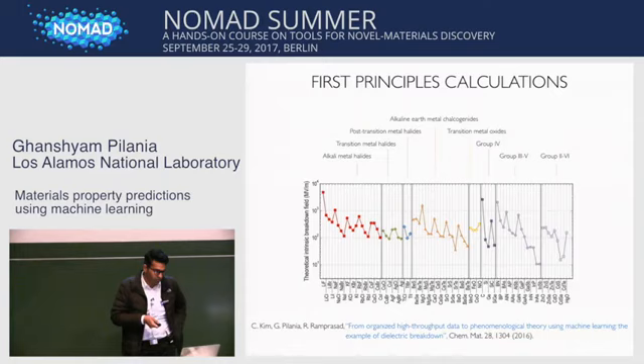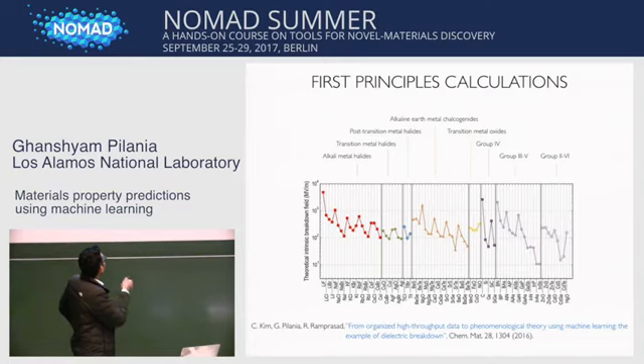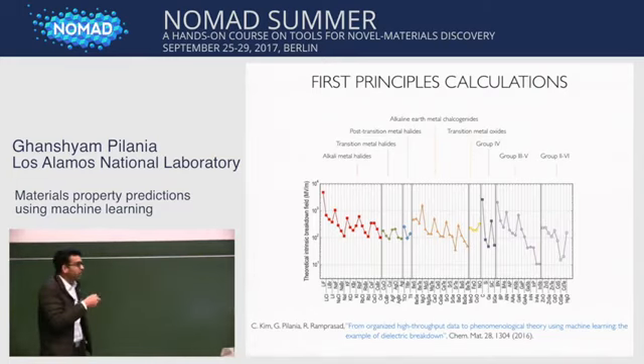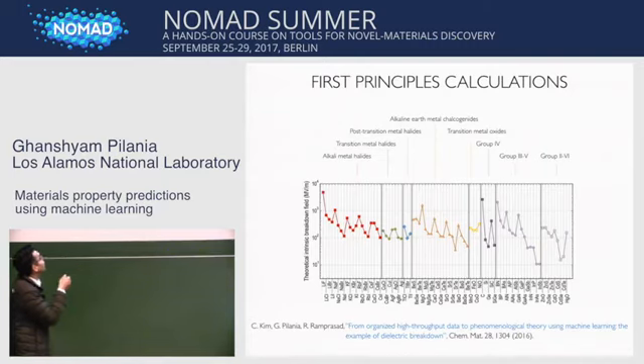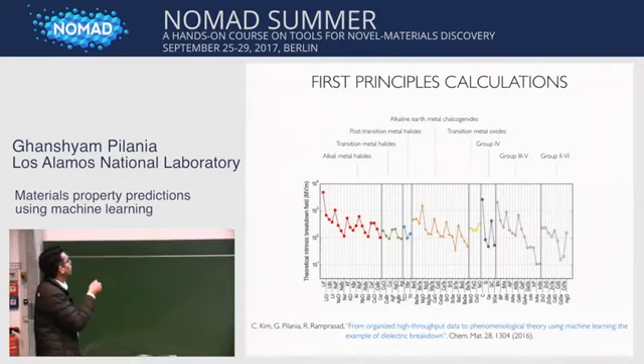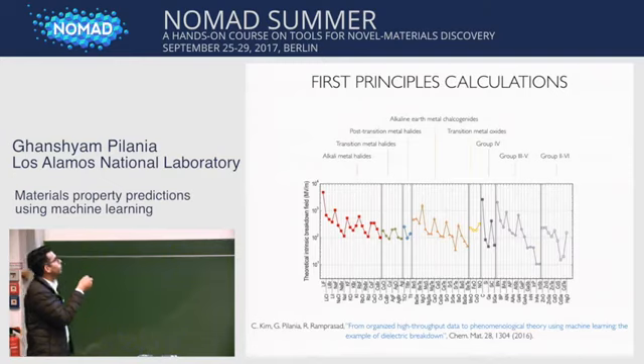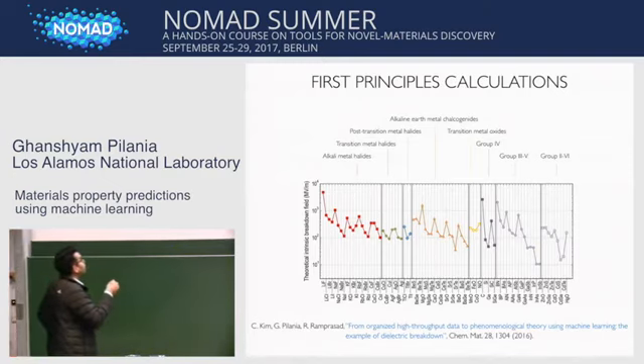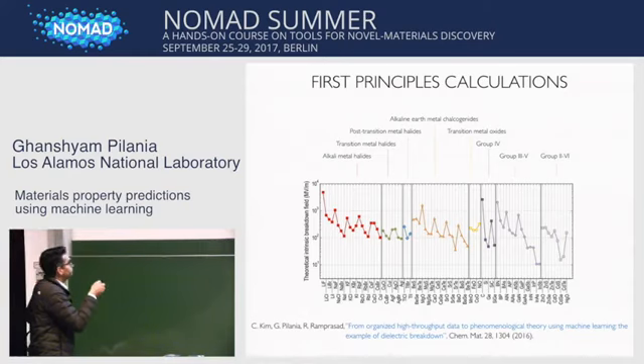So this is the computed theoretical breakdown field strength for all these 82 binary octets. And here the compounds are grouped in different classes. So we have alkali metal halides, and then transition metal halides, group 4, group 3-5, group 4-6 semiconductors, and so on. And in each group we have arranged compounds according to the anions. So we have lithium fluoride, lithium chloride, bromide, iodide, and so on. So you get the idea. And the breakdown field actually varies over about 3 orders of magnitude.